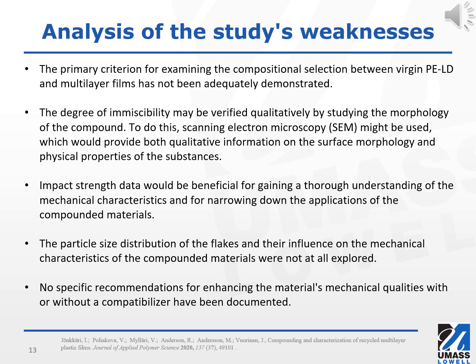So I also want to focus on the study's weaknesses as a part of the analysis. A critical examination of the limitations of the research is presented on this slide. The primary criteria for comparing virgin LDPE and multilayer films in terms of their compositional selection have not been sufficiently proved as of yet. By observing the morphology of the complex compound, one can qualitatively verify the level of immiscibility that exists between two substances, basically the polymers. In order to accomplish this goal, scanning electron microscopy may be utilized.